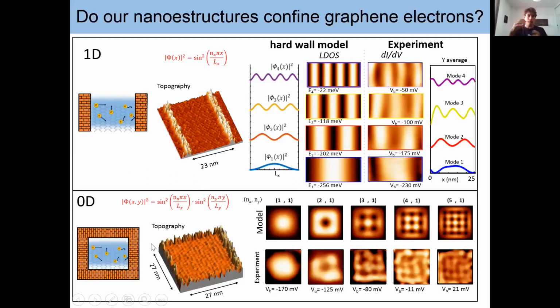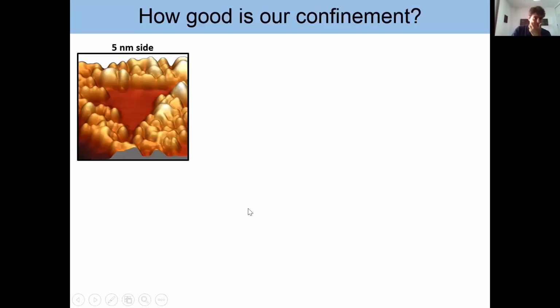And here we have now a structure. Instead of one dimension, we confine in both dimensions. This is a graphene quantum dot in principle, and then we have the different modes that you could see with a hard-wall model again, and this is what we observe in our experiment. So we are confining graphene quasiparticles. Okay, but how good is our confinement? Because we said at the beginning that we wanted to open band gaps. In order to open a band gap in graphene, you need your confinement to be very good.